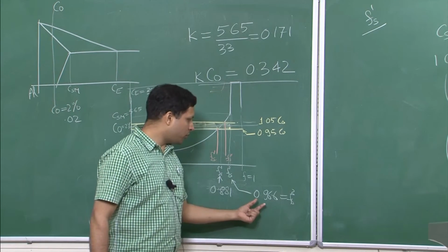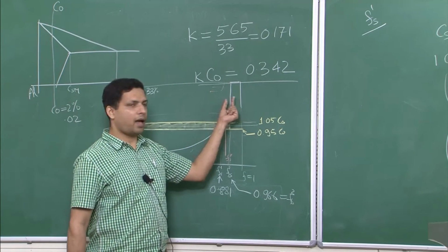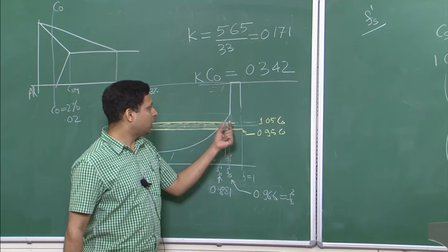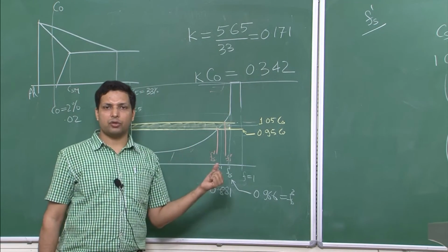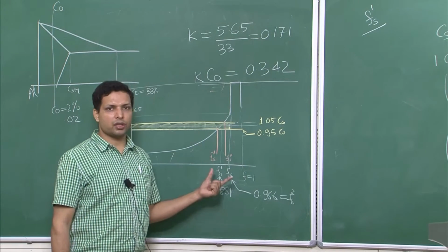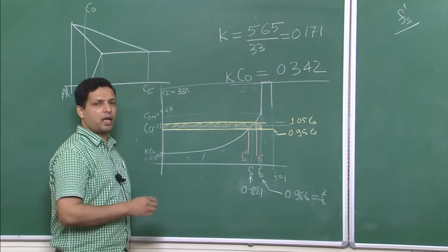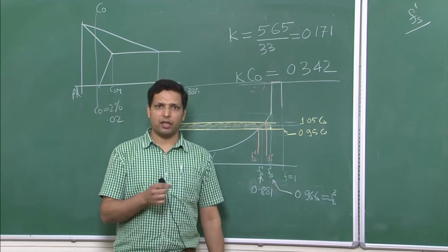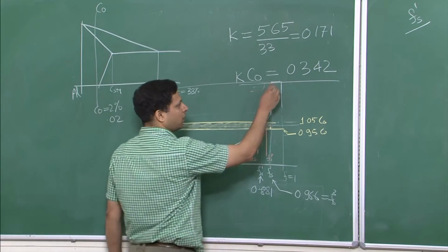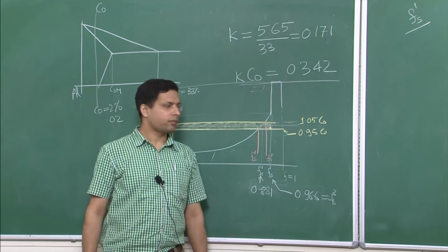So, around 0.034 fraction of the solid has eutectic composition, which means that even in this very small fraction you are able to reach the eutectic composition. That again shows that even though you may have a single phase alloy with very minor concentration of the solute, you may still reach a eutectic composition and a two phase region.